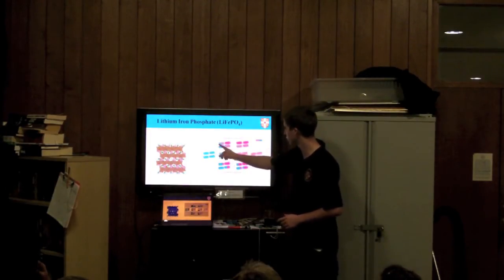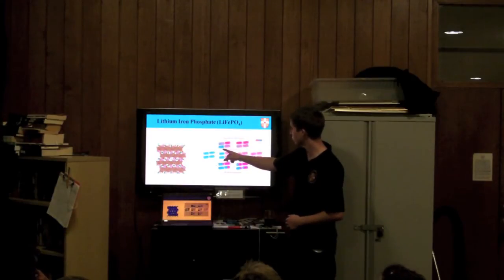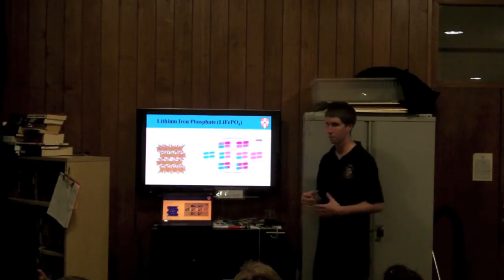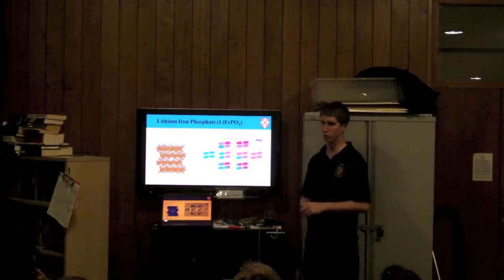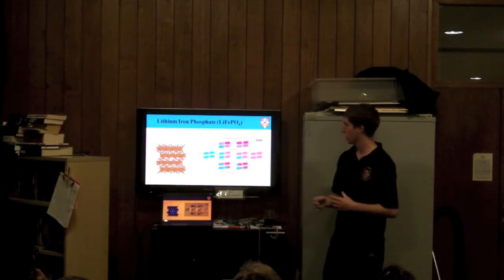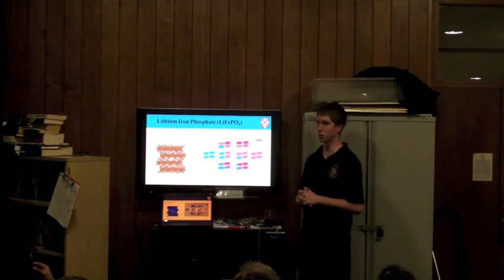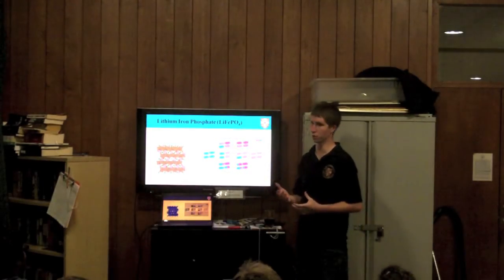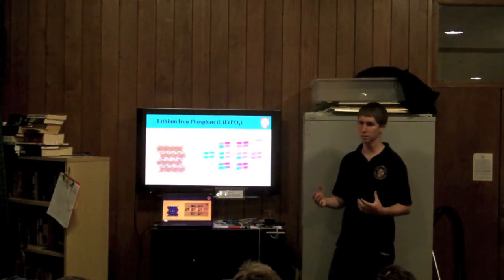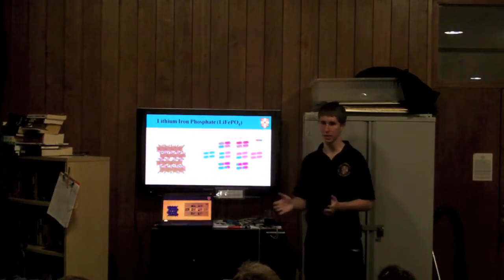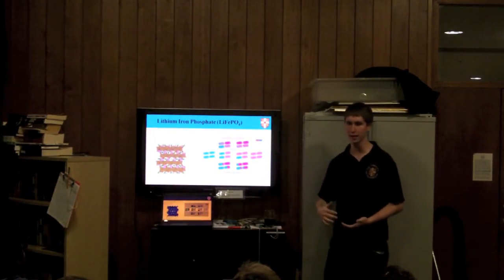So if we ignored the middle and just looked straight at the top, this would be like a solid solution. So we have things that are all the way lithium iron phosphate, and then they kind of go between. And what Hao found, which was actually really interesting, is that it's not exactly either of these. So it goes through like a non-equilibrium solid solution. But all that means is they can go into this in like any quantity, but they pretty quickly relax.